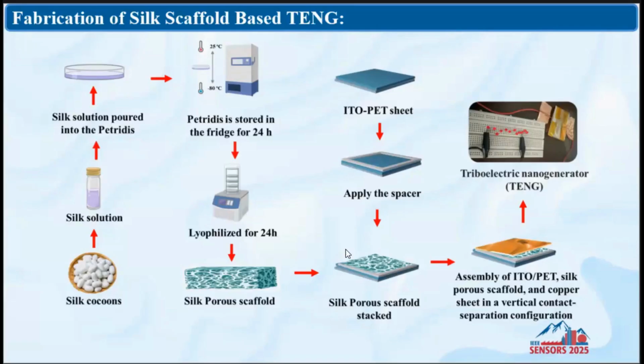Here we have used a copper electrode on the top, and the bottom triboelectric nanogenerator layer is a silk porous scaffold. Okay, and here the copper acts as both a triboelectric layer and, at the same time, an electrode. And here is the structure and assembly of the ITO. On top of that, the bottom electrode has ITO PET, and the top electrode has copper.